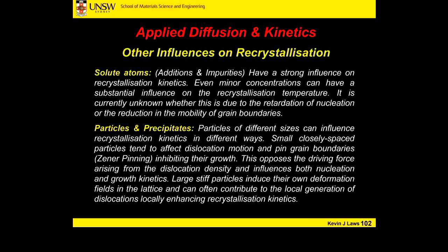So small particles pin boundaries, make it difficult for dislocations to move about, and slow down recrystallization kinetics. Large particles create a stress field, creating more dislocations, which enhance recrystallization kinetics.